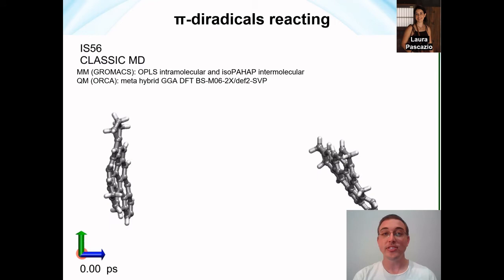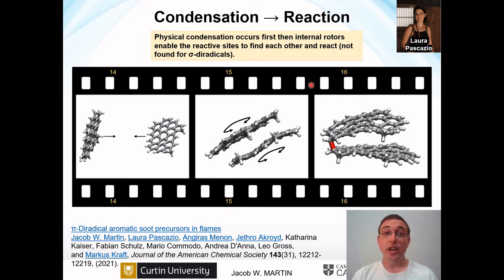So let me just deconstruct that a bit. What I showed you and what we found for many of these collisions is that the molecules first condense, so they actually stick together and form this dimer. And we also find that there's internal rotors, so they're able to rotate relative to one another. And this increases the chance that those reactive sites will actually find one another. And for these size molecules, there's a significant increase in the reaction rate. And we found that this is only possible for the localized π-radicals. It's not possible for a radical where hydrogen's just abstracted from the edge of the molecule.